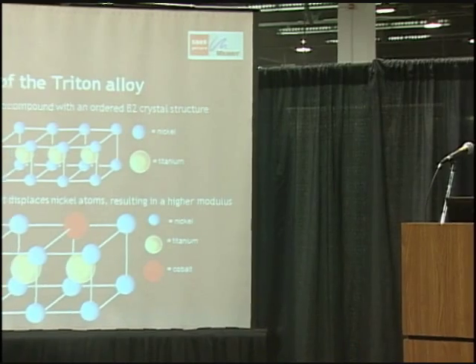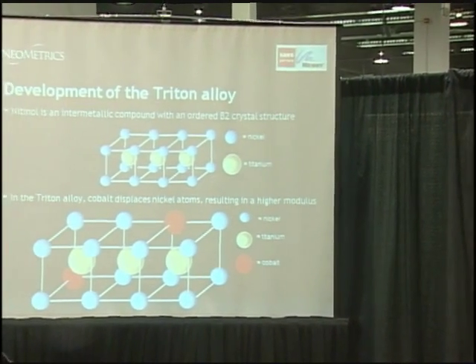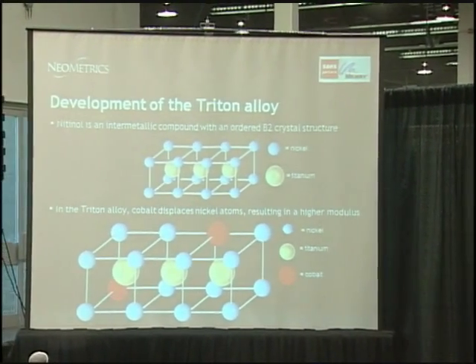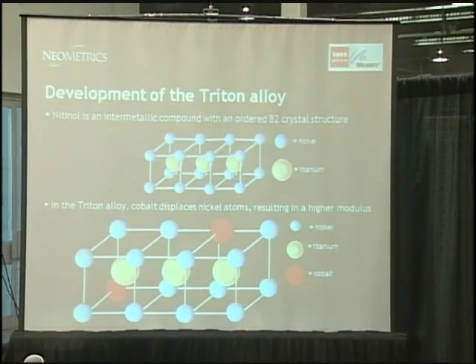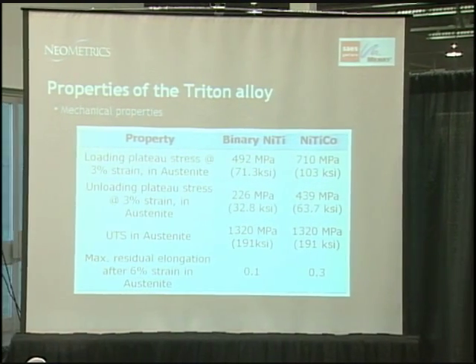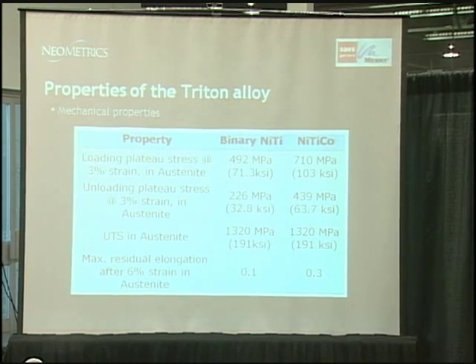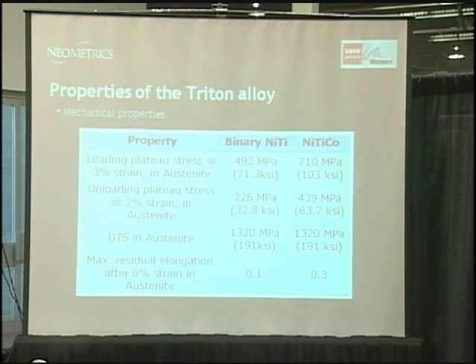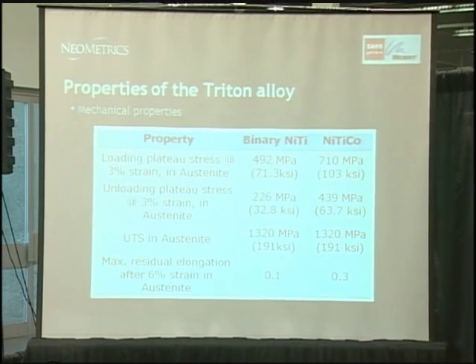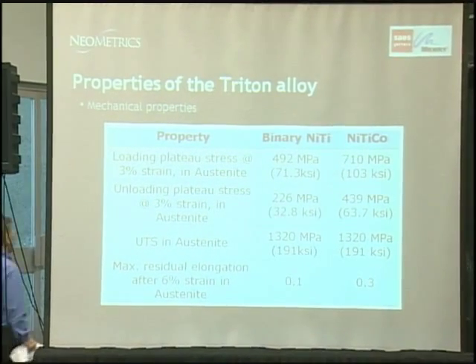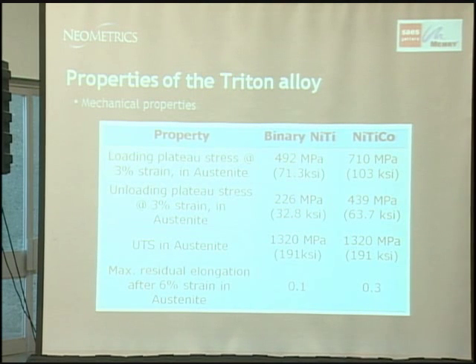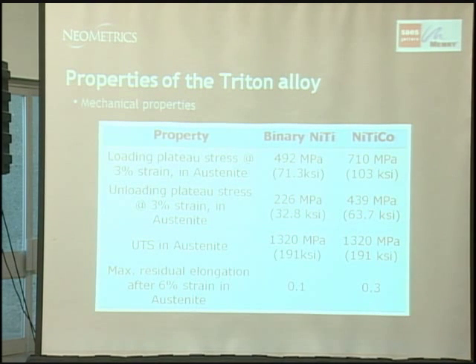As I mentioned earlier, what we've done with this material is we've incorporated a cobalt element to the nickel titanium crystal structure, and as a result of that, we've increased the modulus of the material by about 40%. In terms of some of the actual numbers, the loading plateau stresses for binary nitinol are about 492 MPa, or 71 KSI. This material, at the equivalent diameter at 3% strain, is at 710, a significant increase.